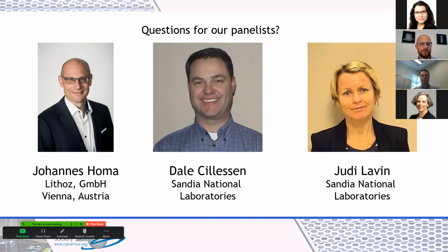So let's see. The first question I think is probably for Johannes. The question is with regard to when you printed the dissimilar materials. You showed an example of a zirconia with an alumina. So the question is, after you printed the part, did you have to adjust the sintering profile somehow to do the finishing of the part?